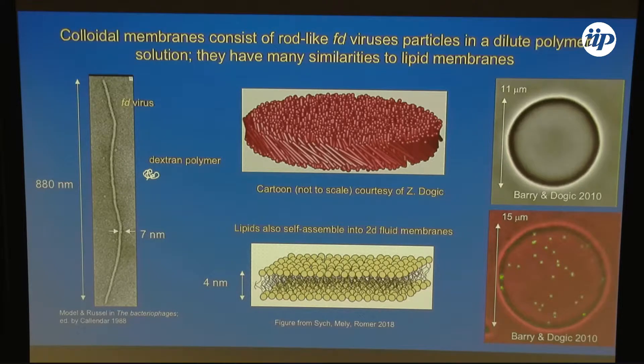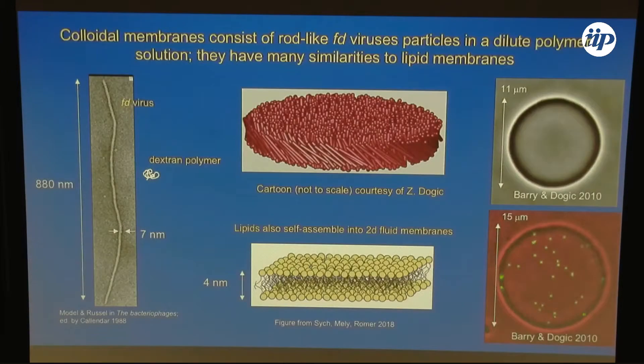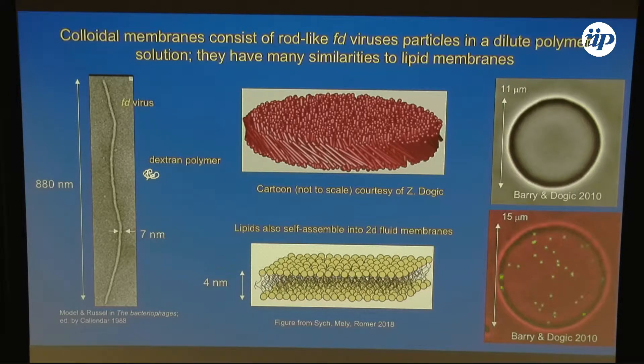Of course, they're not bilayers, and they're much bigger, and they have distinctive properties as well. They have free edges — they don't tend to form vesicles like lipid bilayer membranes, and they typically also have saddle shapes with negative Gaussian curvature. They're suspended in a fluid and are actually a little bit heavier than the fluid, so they tend to sediment. In all the experiments done here, they have a polyacrylamide brush on the bottom which the dextran can penetrate so it doesn't adhere.